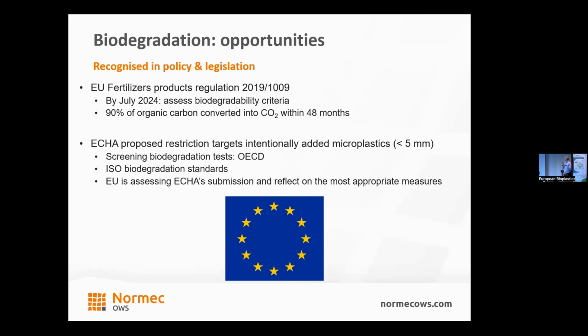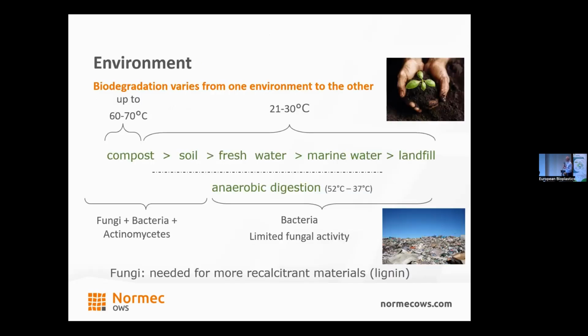The first field is by doing screening biodegradation tests. You have a tiered approach according to the OECD guidelines. However, for plastics, the polymers will not fulfill these requirements, as it's quite a short duration and only aquatic degradation testing. So we are also allowed to follow the standard ISO procedures like ISO 14855 and ISO 17556 in soil. And they have made a proposal. ECHA, currently the EU is assessing this proposal and is reflecting on how to start developing the most appropriate measures. So there's work going on in this field.